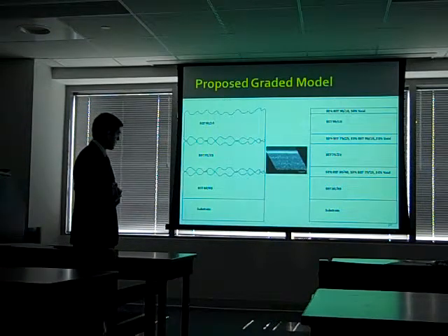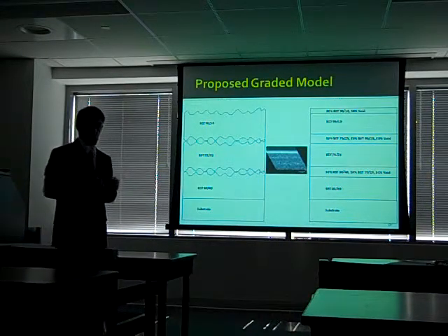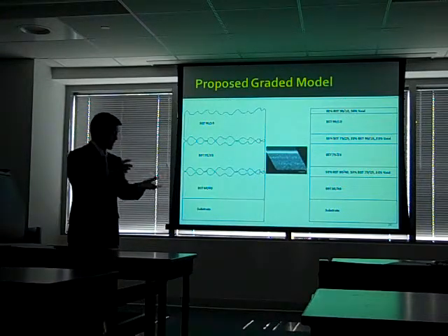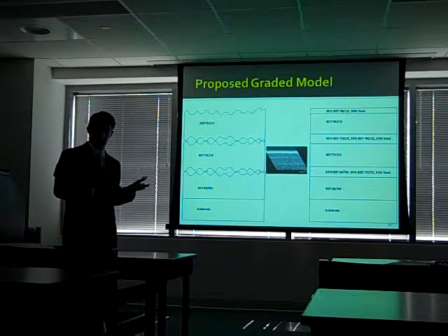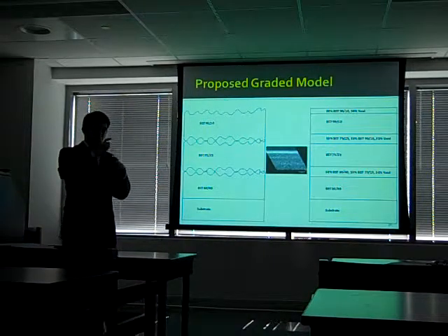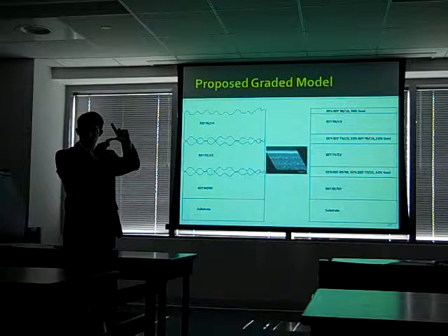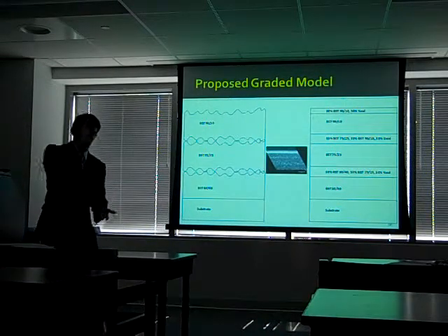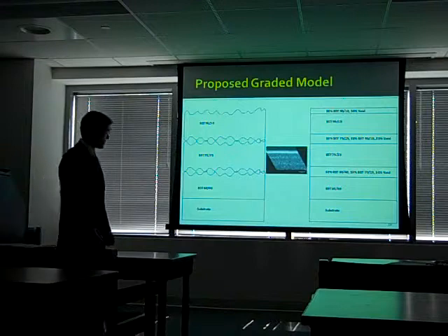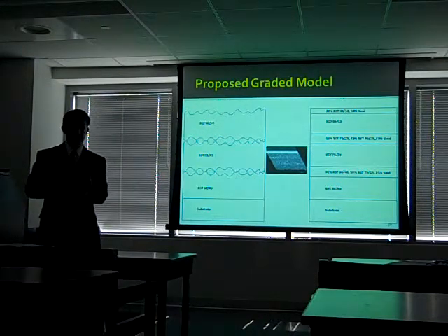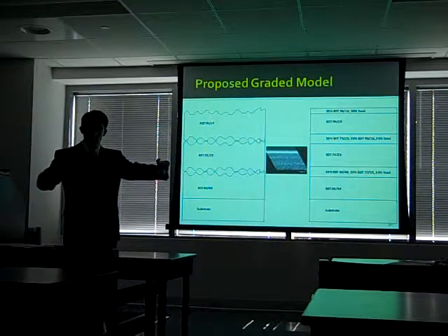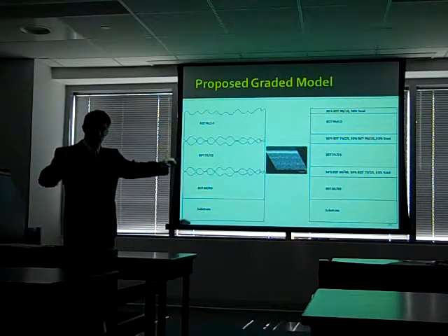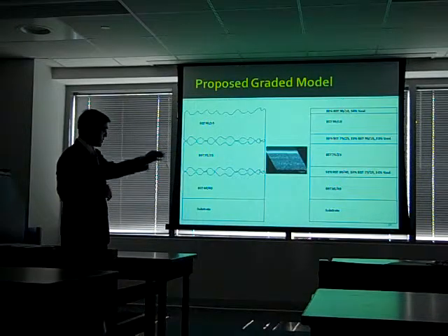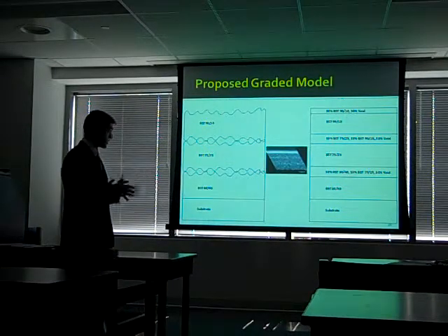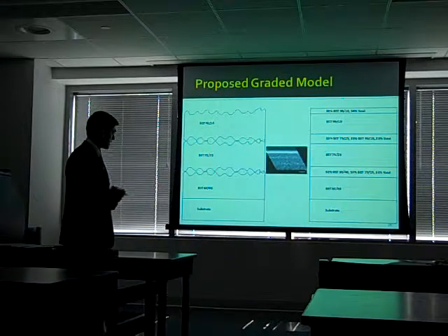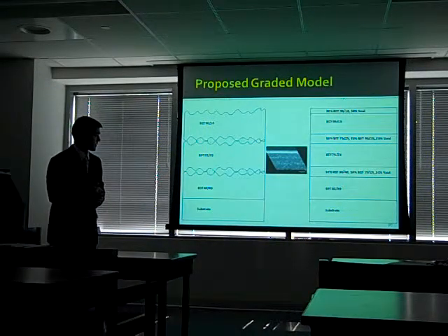One thing I want to point out too is the annealing procedure is crucial with these films. The interdiffusion coefficient of amorphous BST of one composition into another is so high that if you made 3 different compositions from your spin coating process and then had one anneal, you would have, in the end, one homogeneous composition for your film. So that requires a multi-stage annealing procedure. After the first composition is deposited, it must be annealed, and then the second composition is deposited, and then another anneal. So despite this film having been made by that multi-anneal procedure, you can still see this roughness and voids in the middle there.